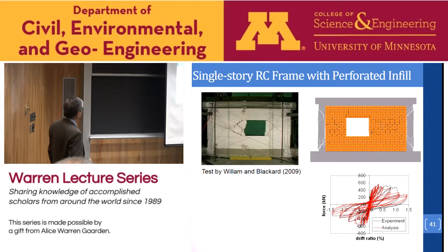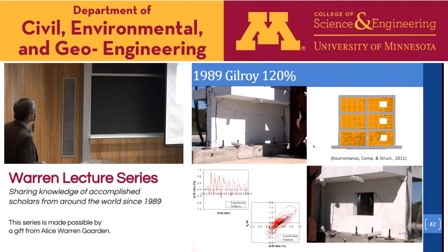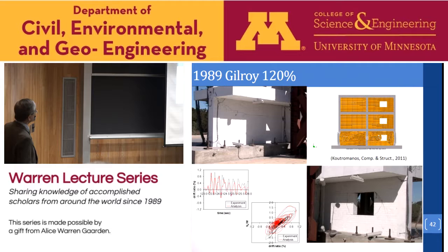So finally, we apply this to the three-story frame we tested. So that was right before the collapse run. So you see the cracks develop here, cracks around the window opening. So we could capture this crack pattern relatively well.